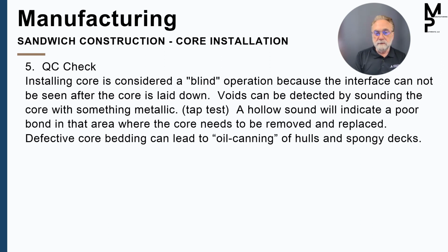Okay, and this is a great time to check your core to make sure it's bonded. Okay, so at this point you could feel it. If the core is loose, you have not bedded it well, you would want to cut that area of core out and rebed it. All right, so this is great. If you can catch it now, it's going to be a real saver in time and money, because if you don't catch it now, you're not going to see it till it's out in the field and you're looking at what could be a very, very expensive repair trying to get to the core in a structure like a boat. Okay, so tap test, feel it, twist the cores. You can tell if it's bonded.